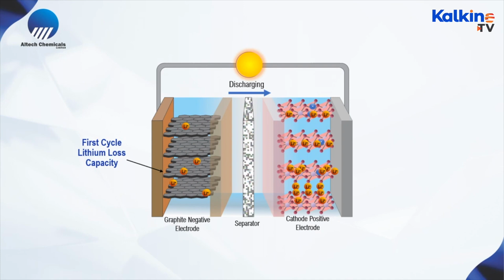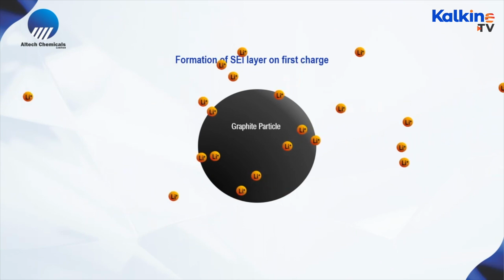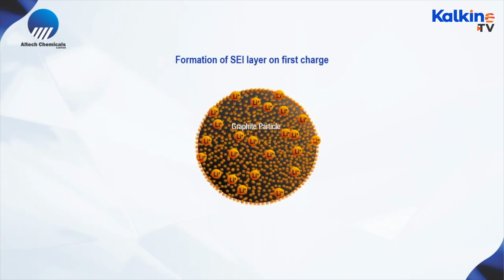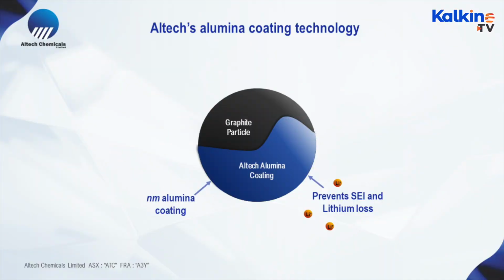But what a lot of people don't realize is that about 8 or 10% of that lithium remains on the anode and becomes inactive to the battery. What it does is it forms an SEI layer around the graphite particles. And once it forms that layer, it becomes inactive to the battery. Now imagine that 10% of your lithium inventory doesn't take any part in the future life of the battery. I mean, this is a real problem for the battery industry, and they've been trying to resolve this problem. Now, our company believes that using alumina coatings will resolve this SEI layer from forming. And we believe that it has game-changing benefits for the lithium-ion industry.